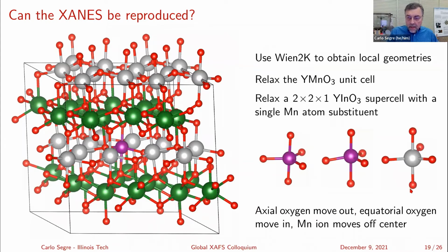So we start looking at the manganese. You can sort of see this environment is relatively symmetric with pure yttrium manganese O3. There are some slight differences here in these distances, but not large. And that's where we start from with the yttrium manganese O3.